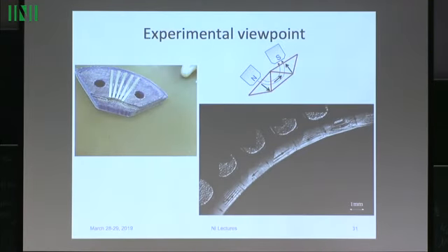So you push it into those magnets, and each of those domains pops in. You push it right in this region, and then it develops this. But without the magnets, it's quite hard to do, because it's not so favored. If you want to try to bend it, it's not easy to create this microstructure generally. And this goes way back many years. We tried to produce this. This seems to be the easiest way.